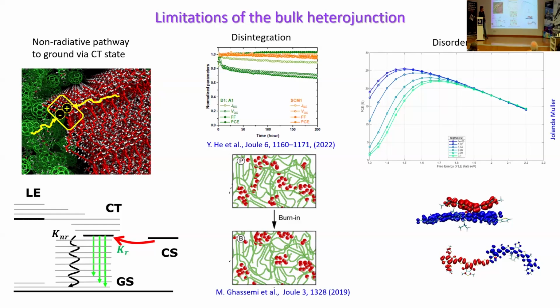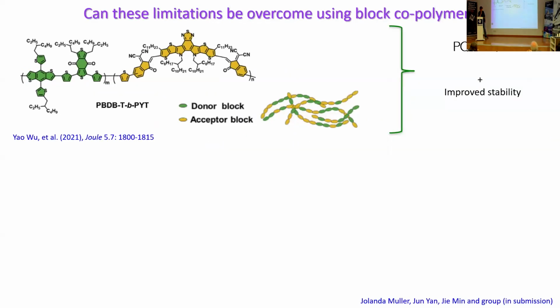And one way to do that, that we've been looking at, is to work with the same molecular units, but rather than having a mixture of one semiconductor and another one created from solution processing, we looked at materials that were made by collaborators in China, Jimin and his group, where the donor and the acceptor are covalently bonded together into a block copolymer structure. So that the way in which the donor and the acceptor interact is actually chemically controlled.